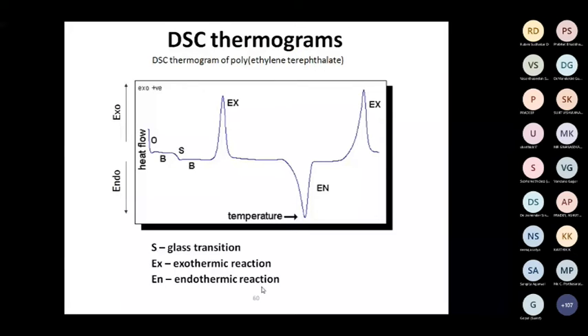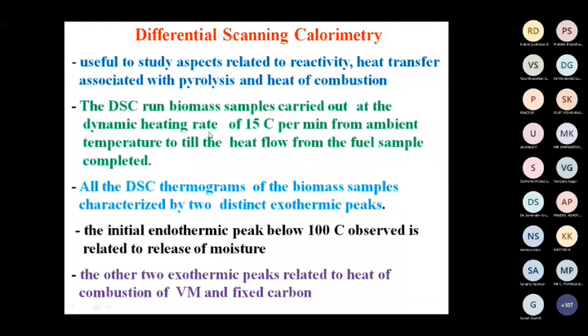So in DSC, these are the exothermic peaks, heat release from the sample. These are the endothermic peaks, heat absorption by the sample. So it is useful to study aspects related to reactivity and heat transfer associated with pyrolysis and combustion. The DSC runs for all the biomass samples were carried out at a dynamic heating rate of 15 degrees C per minute from ambient until the heat flow from the fuel is completed. All the DSC thermograms of the biomass samples are characterized by distinct exothermic peaks, similar to TGA.